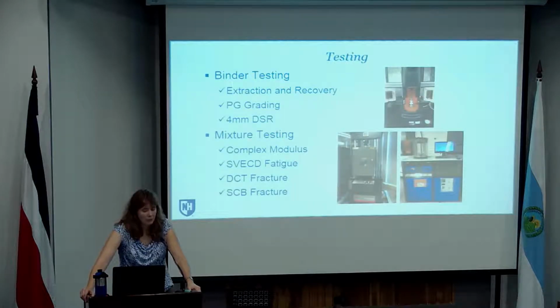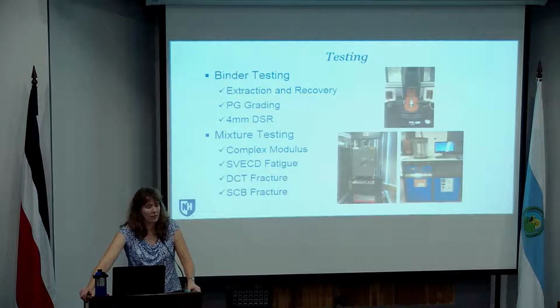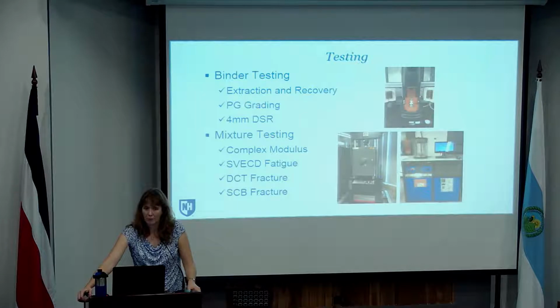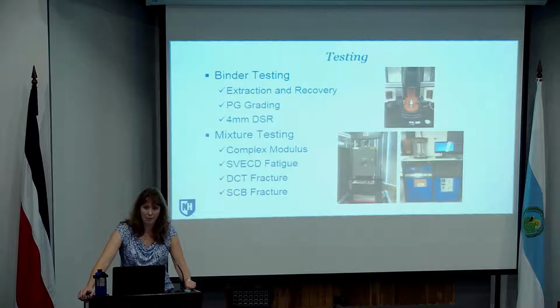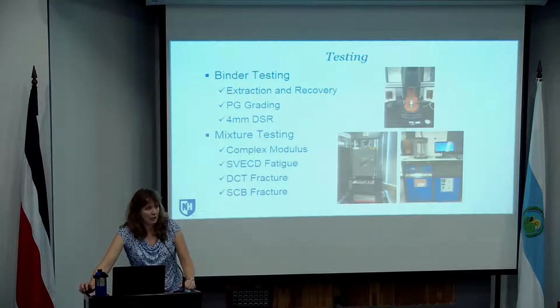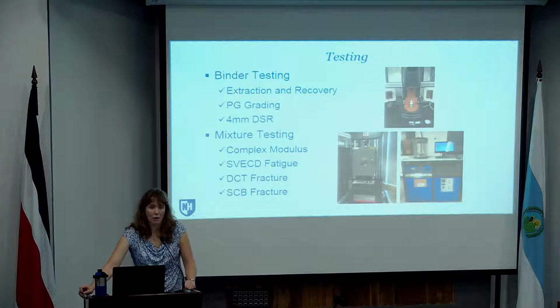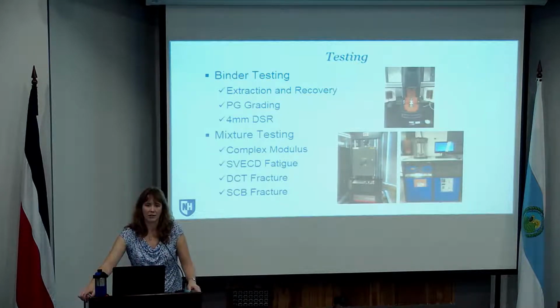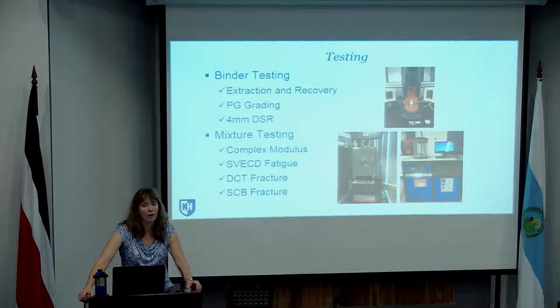In terms of testing that we've conducted, we're looking at both binder testing and mixture testing. Most of the binder testing was extracted and recovered from the mixtures. In the cases where we were able to get the tank material from the plant, we also did the testing on the tank asphalt as well, mostly looking at PG grading, so going through the typical PG grading protocol with the DSR and the bending beam rheometer. And then more recently, we've been looking at using the 4mm DSR protocol to be able to fully characterize the material over a wide range of temperatures and not have to do the BBR testing.